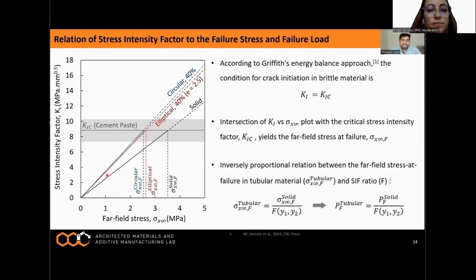according to the Griffith energy balance approach. Consequently, the intersection of the stress intensity factor and far field stress plot with the critical stress intensity factor yields the far field stress at which the crack initiation takes place, as shown by sigma infinity solid. We can see that the stress at failure in the tubular architected materials is smaller than the stress at failure of the solid.